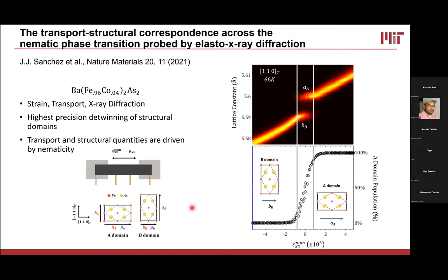So what that means is when I apply tension, I'm going to favor this A domain, and compression will favor the B domain. Now over here on this plot, right here in the middle is applying zero strain. To the right is tension, to the left is compression. When I'm at zero strain within the nematic phase, and I do an X-ray diffraction measurement along the stress axis, I get data that looks like this. So you have to imagine that this is a single line cut right here, which is showing two peaks.